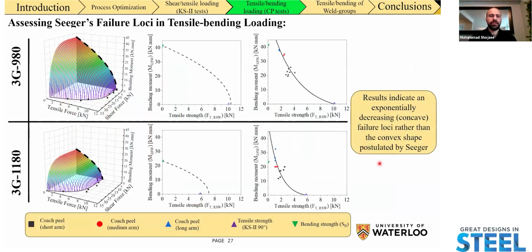So now, if we add all that data into the failure loci that we had initially, we can really tell that the initial convex shape that was postulated by Seeger in terms of the behavior of the spot welds in tensile bending loading conditions does not really hold. On the right-hand side, you can see the data points for the three different geometries of the coach peel. The black is the short arm, the red is the medium arm length, and the blue is the long arm. You can see that the trend we're getting is more of a concave shape that better predicts the behavior of the spot welds in terms of their tensile bending loading condition.